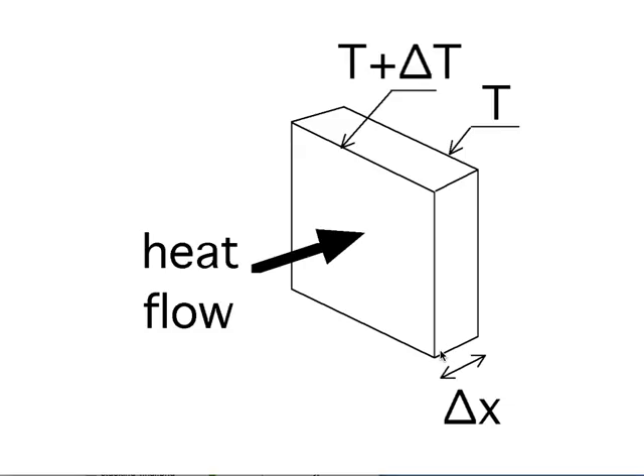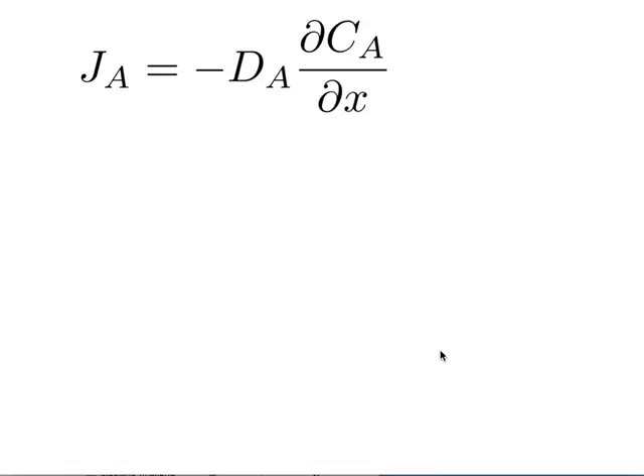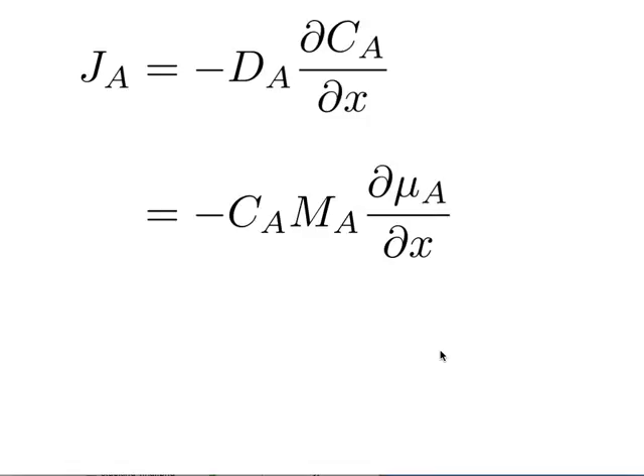Okay, and here's another example where we have heat flow being driven by a temperature gradient, delta T, and that obeys Fourier's law, which tells you that the heat flux is proportional to delta T. And we have Fick's law of diffusion, where the flux is proportional to the concentration gradient. Now, we know that actually it's not proportional to the concentration gradient, but to the free energy gradient. So, instead of Fick's law, we write that the flux is proportional to the gradient of the chemical potential, d mu A by dx, and that constant is called a mobility. So instead of the diffusion coefficient, we have a mobility.